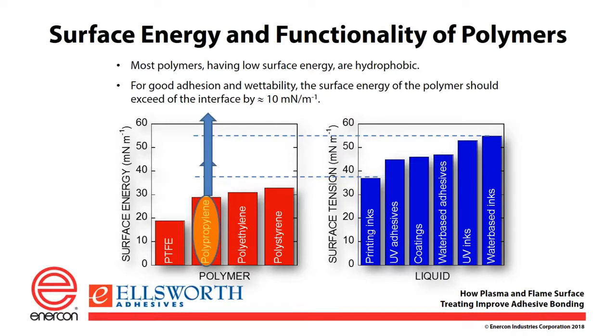This slide is a little complicated. Pick any material, say polypropylene, and it has a surface energy prior to any treatment of approximately 30 Dyne. And then you go to the right-hand side and you pick maybe a UV adhesive. Well, a UV adhesive recommends that you need at least 45 Dyne in order to get a good bond onto anything. So if you're at 30 Dyne with polypropylene and you need at least 45, we need to increase that surface energy. And a good rule of thumb is to increase the surface energy by 10 Dyne or so. So in this case, we might want to increase that polypropylene from a 30 to maybe a 55 Dyne in order to achieve good bonding.